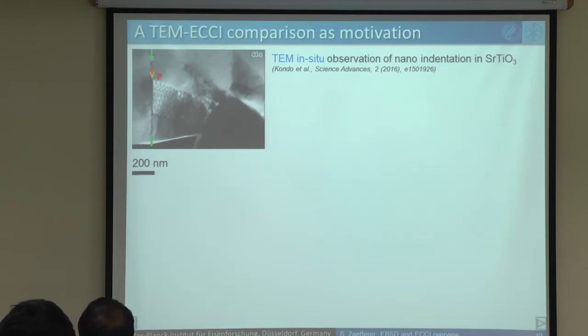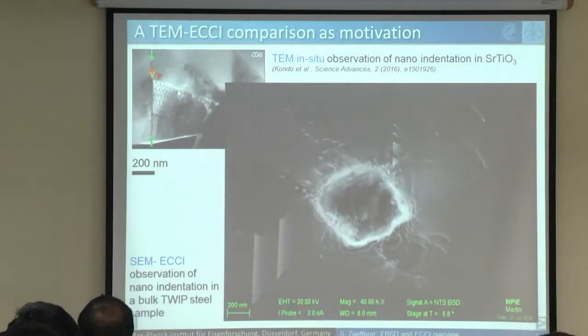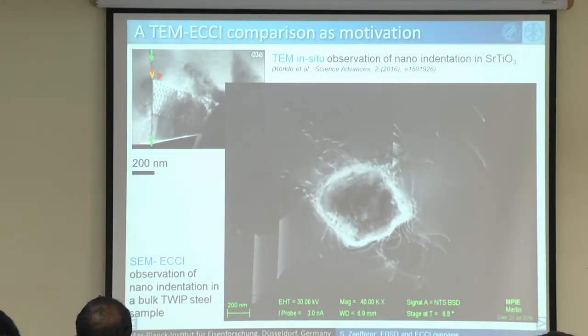And now we cannot do the same thing with ECCI, because currently I don't see yet a proper way to see dislocation evolution in situ. Because while the indenter is there, you cannot look onto the microstructure. Well, there's maybe possibilities, but currently not. At least I have not explored. But what you can do is you can indent and then withdraw the indenter and look on.